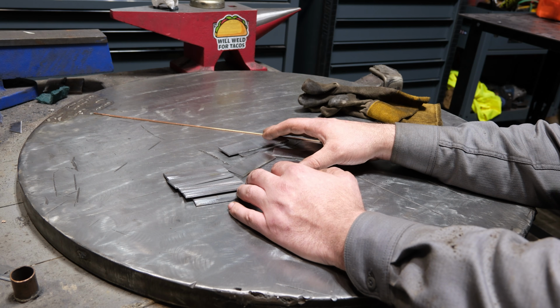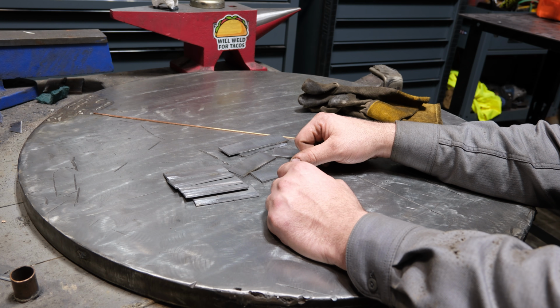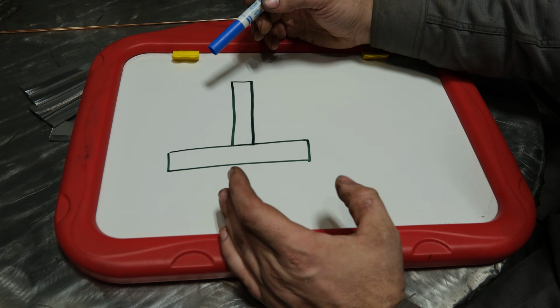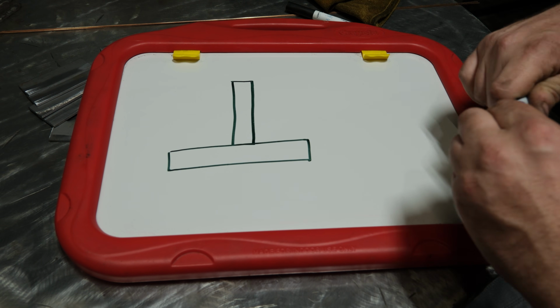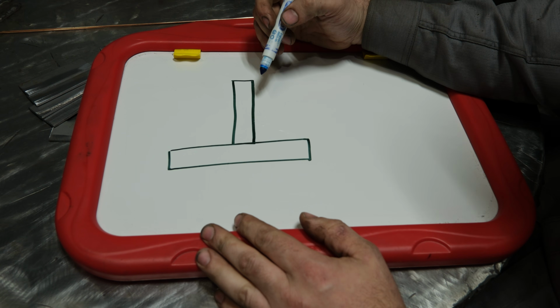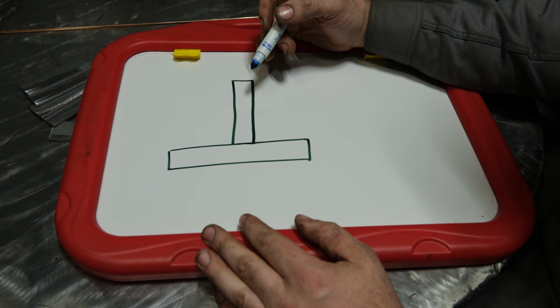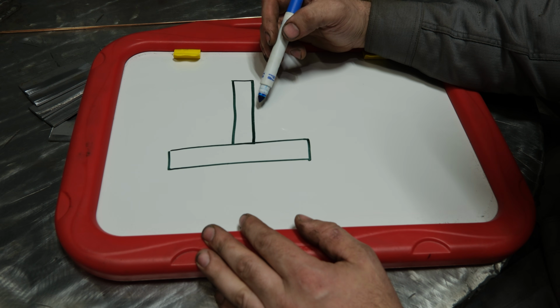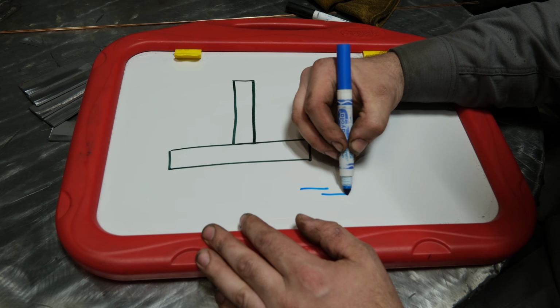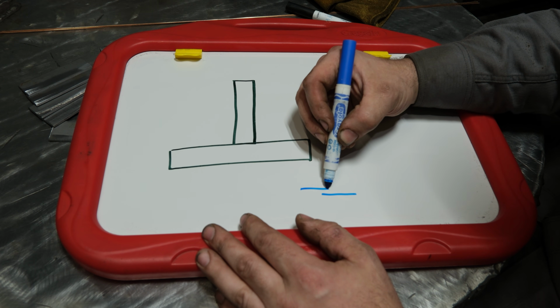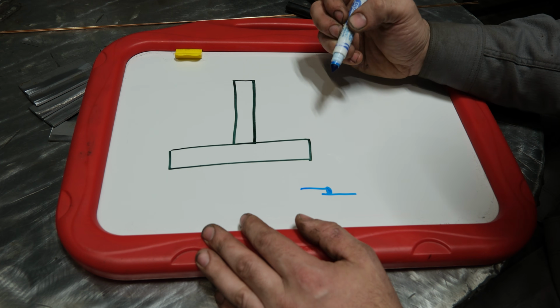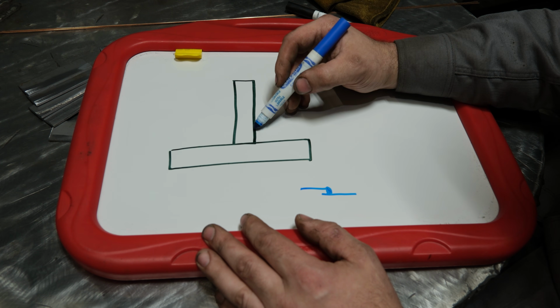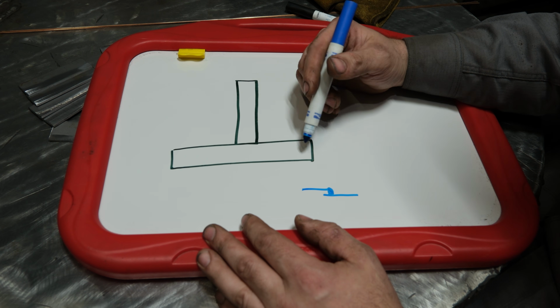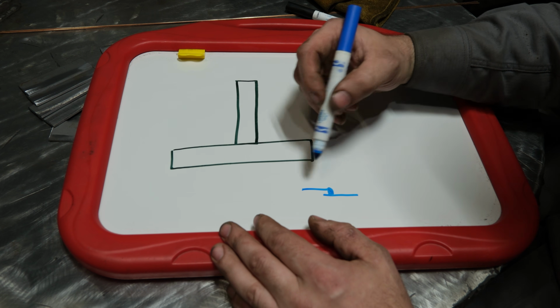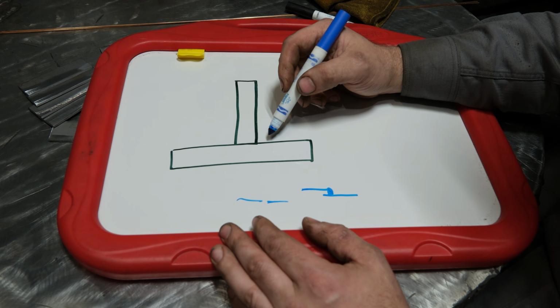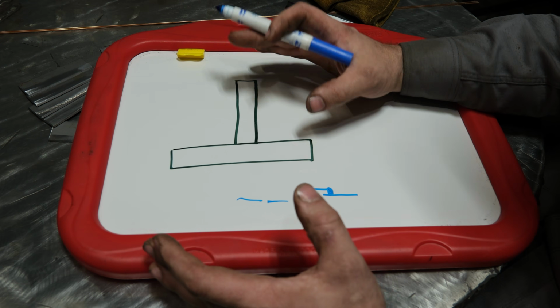Before I get into the actual welding, let's do some quick book learning so we're all on the same page. Depicted here is a common fillet weld or a T-joint, depending on what you call it. These are deceptively difficult to weld when you're new, because guess what? If you've done lap welds, those you can melt the edge of the plates off. So if you have two plates like this, bad habits can be formed because you can just melt this off and make a decent looking weld. However, there is no edge to melt off on this. Therefore, most people, after they switch from doing lap welds or just straight butt welds, their beads look like crap on this. There's no other way to put it.